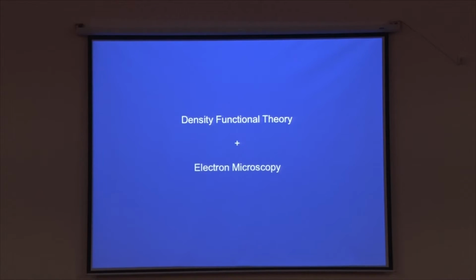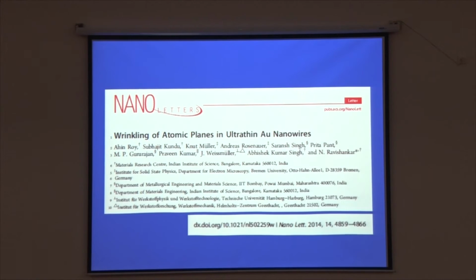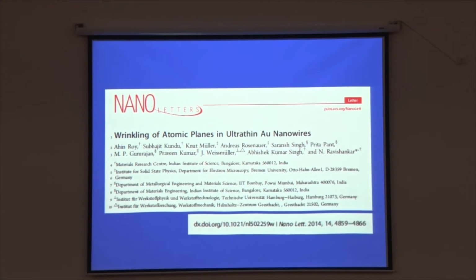Umesh talked about the use of density functional theory for looking at the relaxed structure of different crystals and so on. We use a combination of density functional theory and modern electron microscopy, which is really powerful, to look at the kinds of displacement that are predicted by DFT. I'll tell you the story first, and then I'll go through the details quickly. What we found is that in a crystal, planes are planar. That's why they're called planes.